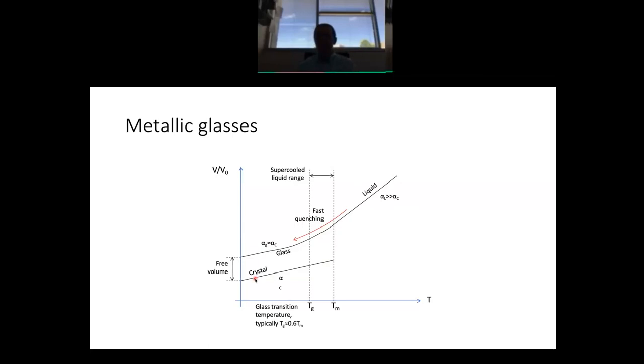If I go to very fast quenching, and by fast I mean very fast, like 10 to the 6th per second or so, I may be able to get the liquid to undergo glass transition. Right? So rather than crystallizing, it simply undergoes this sort of gradual change in volume that interpolates between whatever the thermal expansion coefficient was in the liquid to whatever the thermal expansion is in the solid, through this sort of continuous transition with no discontinuous change in volume. Okay, the material that I have left over is going to have some excess volume in it, called free volume.